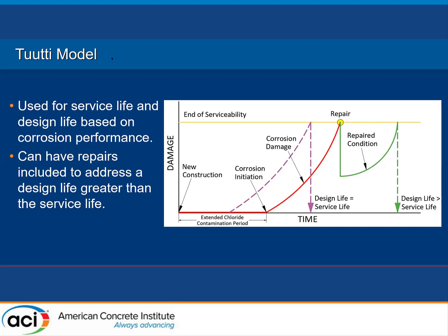Tuutti was one of the first to look at it. There have been modifications of this model, but this is a pretty good model. It has damage on the y-axis, and then it has time. Typically, you're going to have an initiation time, then a propagation period, and then you get to the end of serviceability. Other times, you might get to the end of serviceability, but you say repairs are acceptable at that point, and then you can get more service life with the repair, and eventually get to your design life of the structure. It can either be here or here, depending on how you define it. Typically, for hard to reach components, you're stopping over here. So if you have substructure components, you might want here. A deck might be over here, where you can easily get to it.